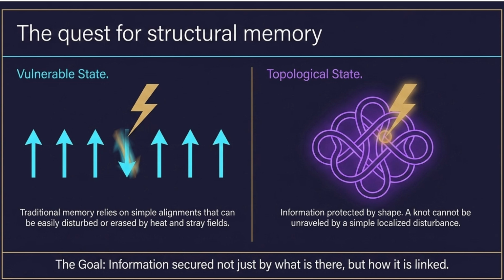The story really gets interesting when scientists started forcing these compass needles into incredibly tight spaces, which creates severe conflicts. Oh, I see. Yeah, a major breakthrough on this front was published in Nature in 2016 by Yadav and a team of researchers. They engineered these specialized superlattices by sandwiching alternating ultra-thin layers of lead titanate and strontium titanate. So by alternating those materials at the nanoscale, they were basically trapping those electrical dipoles in a microscopic tug-of-war. That's a perfect way to put it.